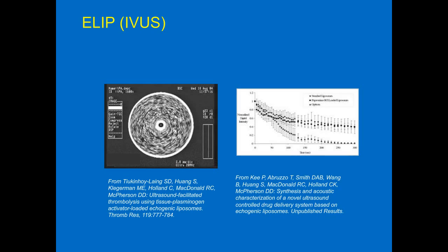Now, in vitro, you could simply take a suspension of these liposomes and put them into a vial. And then using one of these catheters, you can show the reflectivity of the agent. And this can be quantitated because we can use video densitometric methods to get a mean grayscale value for the average area of this.